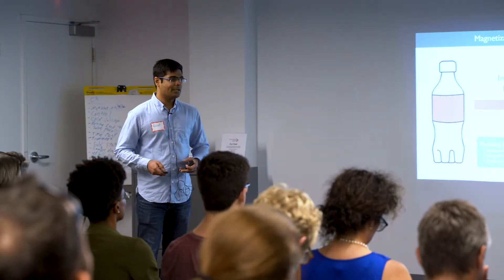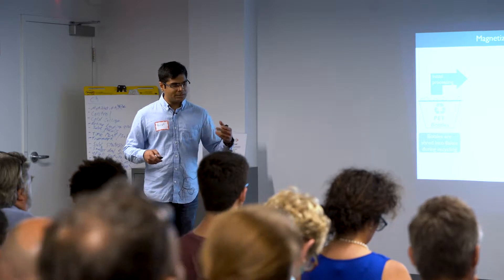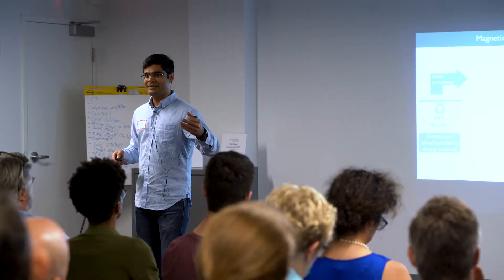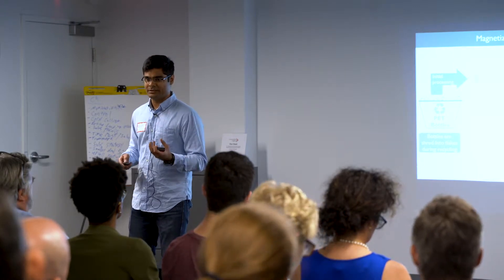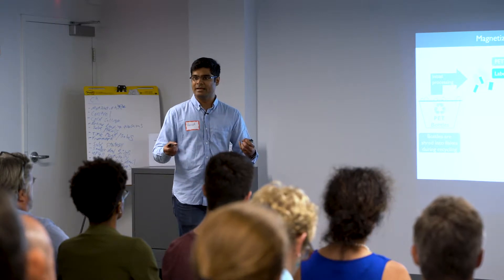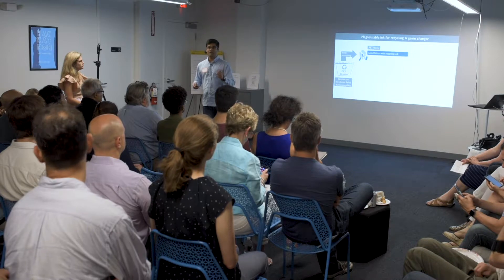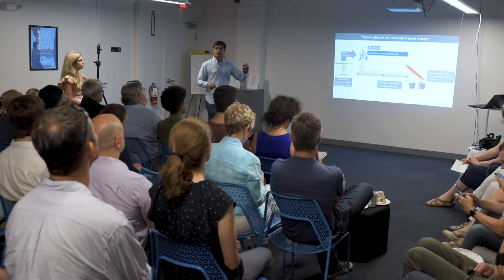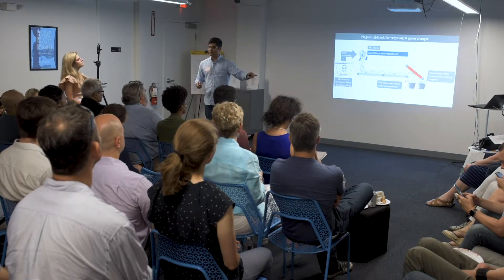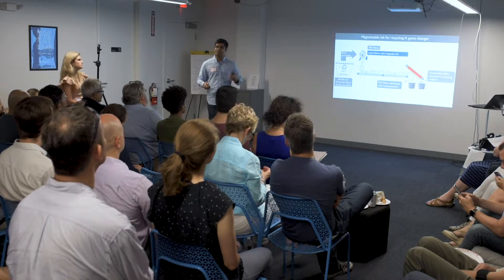We have a patent around it. The way this works is: when packaged items such as bottles are collected for recycling, they first get shredded into flakes. You have a mixture of your PET bottle flake and the label flake that needs to be separated from each other. Our magnetic ink on the label allows the use of a simple magnetic separator that already exists in current recycling infrastructure, utilizing that as a design element to simply pull the label out.